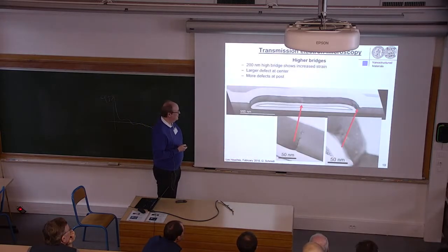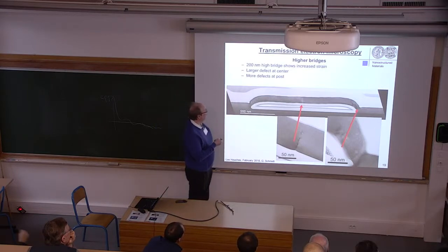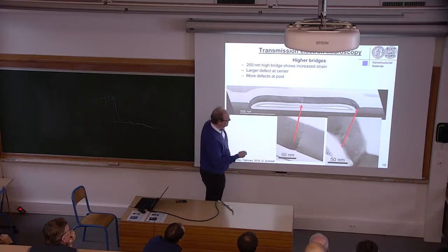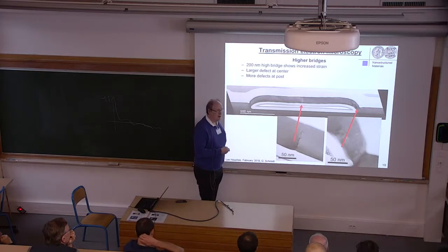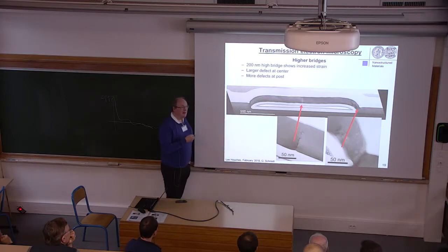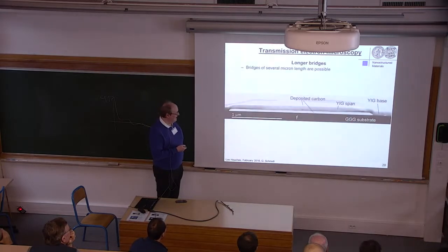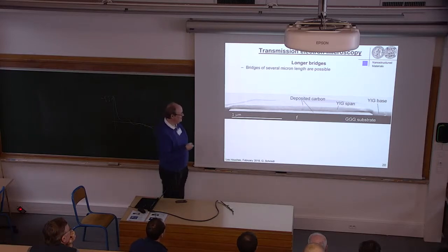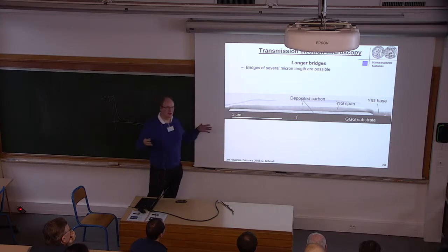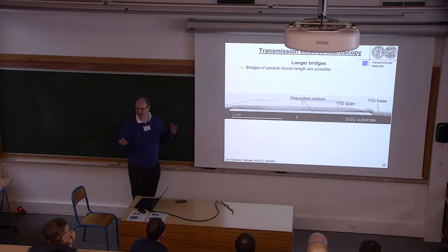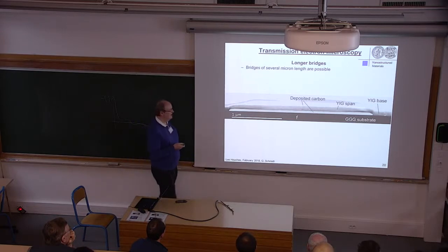As I said, we can also do higher than this. This is almost 200 nanometers high. There you can see the strain is much bigger, so there are tons of defects here. But still, the span is crystalline, but the defect in the center is now much worse. It's really about the height. If we make it long, then the center is more or less like for the other short one. This is about 2.5 micron. So you can see that we really have a large choice, and we can probably design the mechanical properties of the system that we want to have in the end.